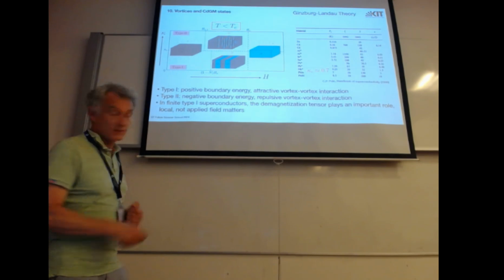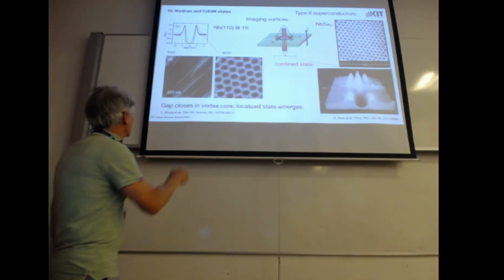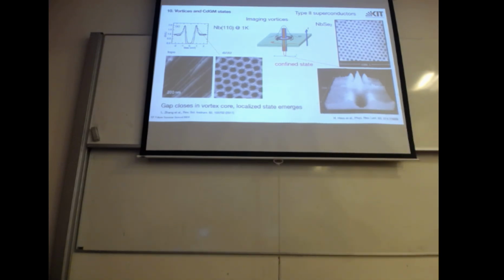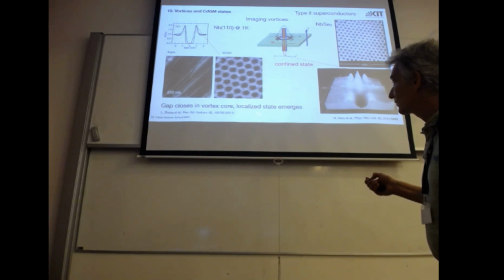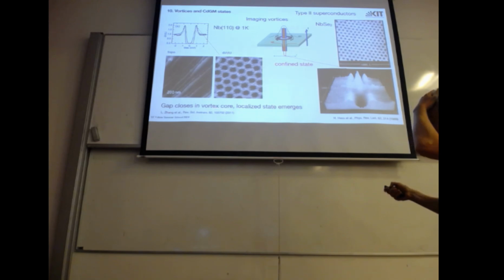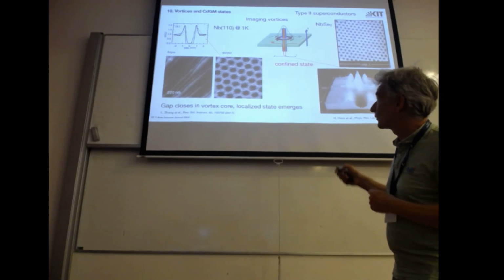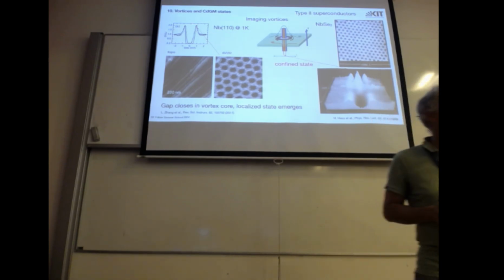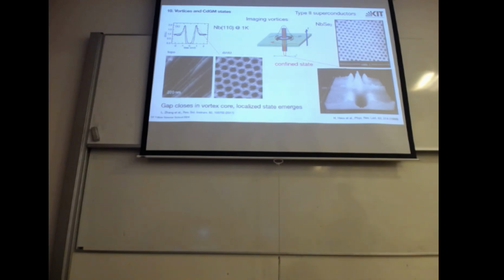So let's take one of these two superconductors. Two superconductors, niobium and another. There are many examples, so I picked two. One from my own group, which is actually not about superconductivity. This is just a characterization of our instrument. We took a bulk niobium crystal, this is topography, and we sit with a differential conductivity outside the gap on the quasi-particle peak, and now measure as a function of position the differential conductivity where we have applied a magnetic field. So if it's superconducting, there's a large differential conductivity, which is color-coded white.